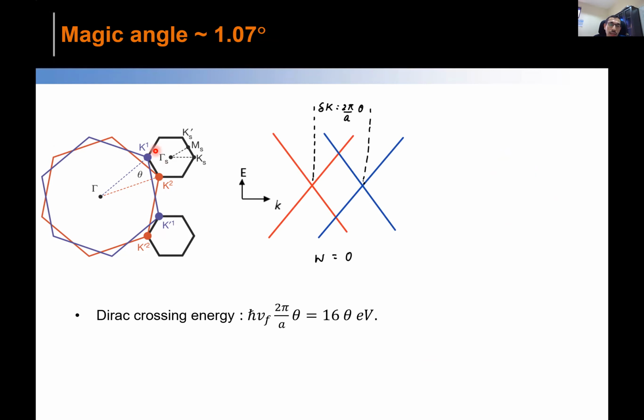As I was saying, the two Brillouin zones of your intrinsic graphene are now shifted because of this twist angle. If I look at the dispersion in an E-k diagram, here the y-axis is the energy and the x-axis is the momentum axis. You can see there are these two Dirac cones from the two layers, one from the top and another from the bottom, and they are shifted, right? Because of this angle, you can calculate this shift: it is 2 pi by a times theta, because this is your reciprocal lattice vector. So this momentum mismatch is nothing but 2 pi by a into theta.